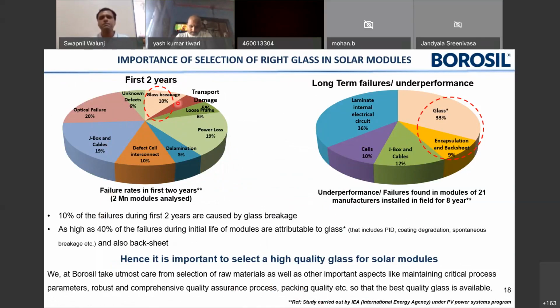But if you do this study for a longer period, let's say 8 years, they did it for 21 module manufacturers globally. They found that glass, encapsulation and backsheet contribute 40%. When I say glass and encapsulation and backsheet, it not only has the breakages, but it also has PID, coating degradation, spontaneous breakages, etc. So if so much of a portion is prone to failures, it is very important to select high quality glass as well as backsheet and encapsulation for your solar modules.